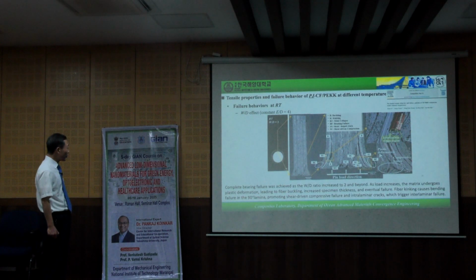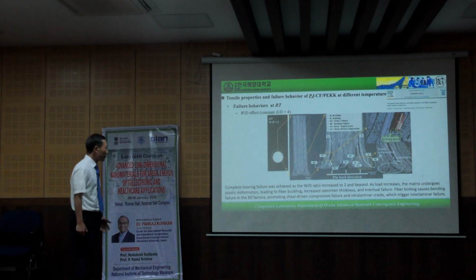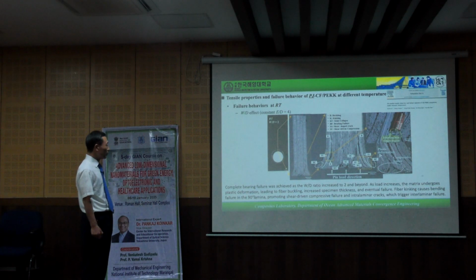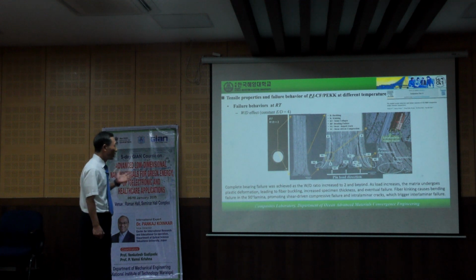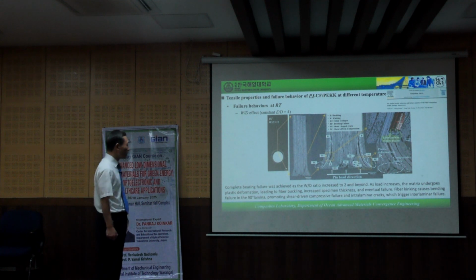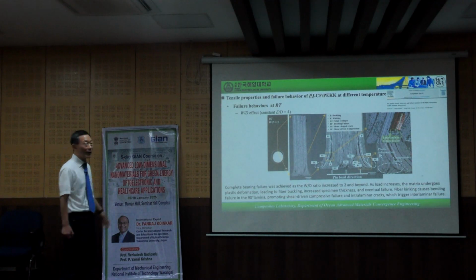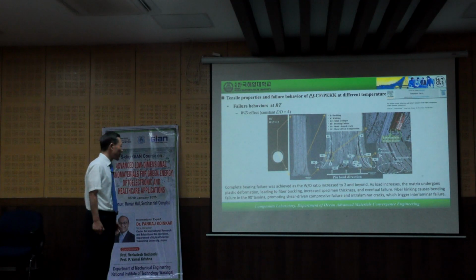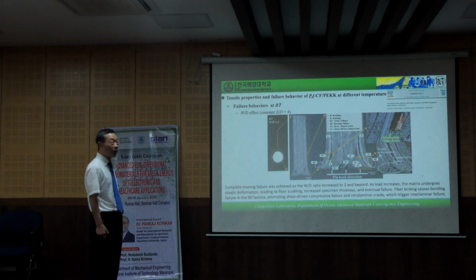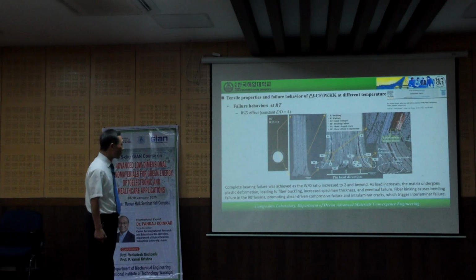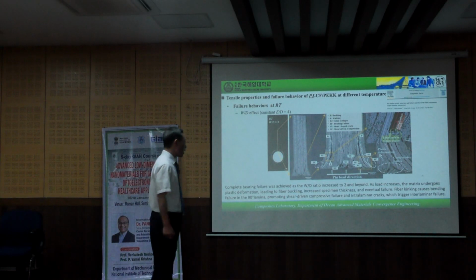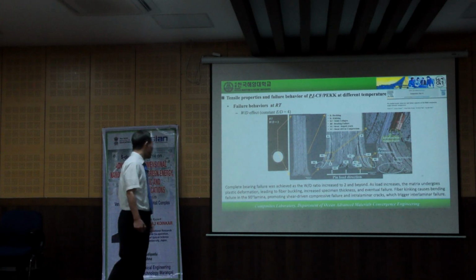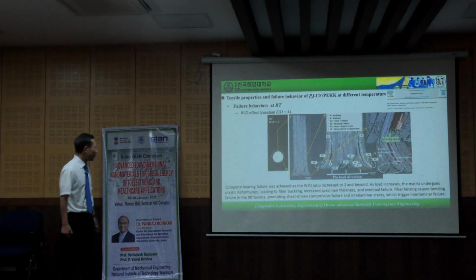So complete bearing failure was achieved as the W/D ratio increased to 2 and beyond. As the load increases, the matrix undergoes plastic deformation, leading to fiber buckling and increased specimen thickness and eventual failure. Fiber kinking causes the bending failure in the 90-degree lamina, promoting the shear-driven compressive failure.